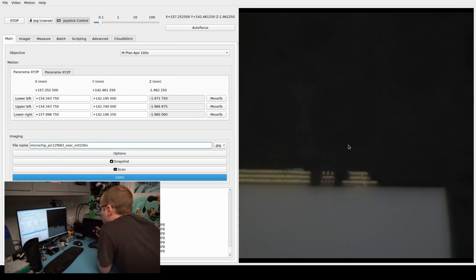And then moving to the right side, we can see the last little bits of power interconnect, and then a couple of other signals near the perimeter, and then the seal ring on the right side of the die. And I was very happy with the quality of this corner. The longer polish at the P2500 definitely made a big difference on surface quality. There's no chipping or cracking or anything visible at the corner. It looks flawless.